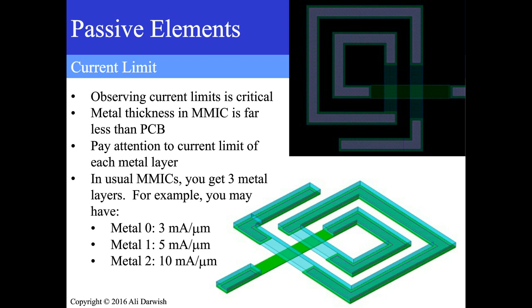And so you find that to be able to sustain the amount of current that you need, you need the lines to be much wider. Because in the MMIC process, the thickness of the metals are just a few microns. And if you talk about the bottom metal, it may be limited to even less than 1 micron of thickness. And so current handling limitations for conductors on MMICs is something really important, especially for power circuits.